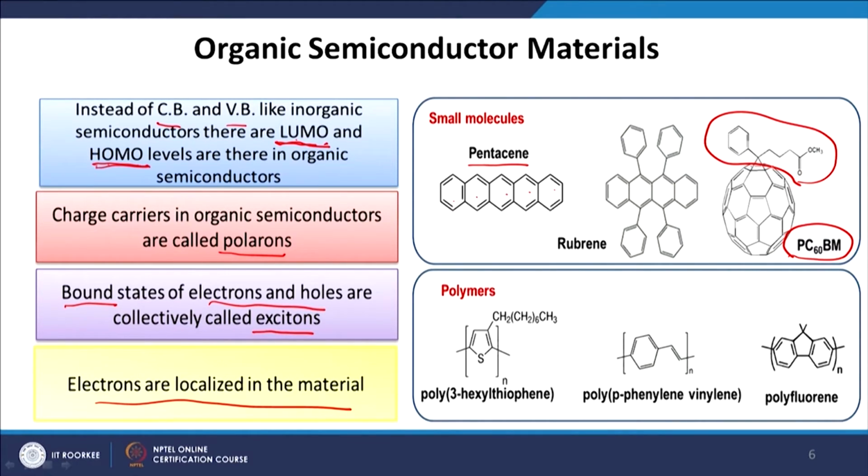So, then we anchor or conjugate a side group, usually an alkyl group, onto the fullerene moiety, and what we get is the PCBM. The solubility and absorption of the PCBM are much higher than the C60, and this is a common material of choice as an acceptor material in organic solar cells. Now, let us come to the polymers.